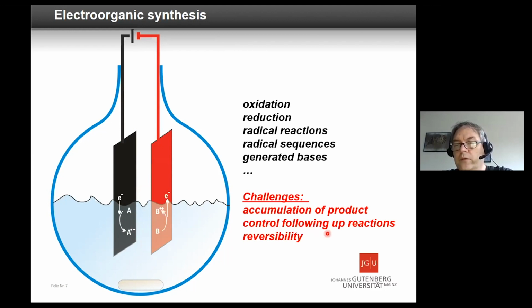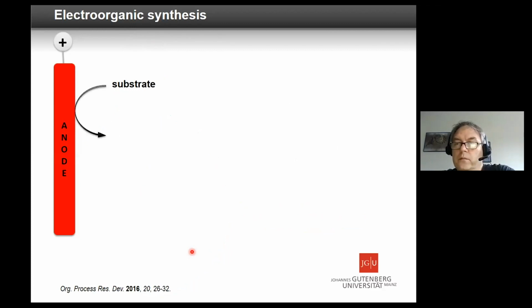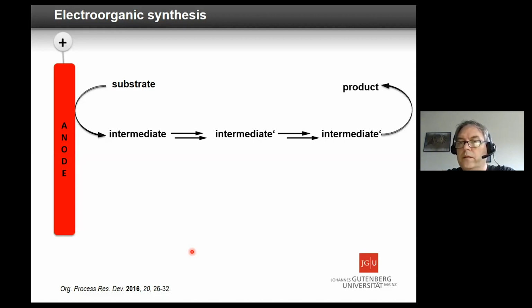That means control of the following-up reactions is very important. It could be that the product is eaten up by the counter electrode, but also at the same electrode on a longer time scale. And this is not reflected by CV studies. Therefore, you have to test this. You have to do electrosynthetic testing. And what is the important thing about that? Well, usually in the textbooks, electrochemistry is taught by a physical chemist, and everything happens on the electrode. In organic chemistry, electrosynthesis is a little bit different, because the radicals are quite stable. Then you have intermediates, and the intermediates have an afterlife, which is not on the electrode, but close to the electrode or in bulk.